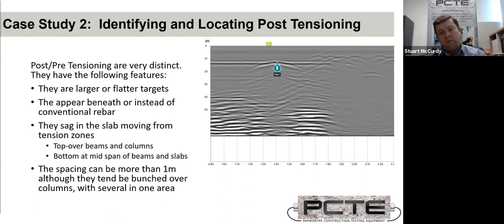So the first time you find them, close to an edge, they're going to be closer to the surface, and then they're going to move down and then come up again. Also, they're irregularly spaced. So with rebar, every 150 mil, you're expecting another one. With post-tensioning, you might have a bundle together, and then nothing for a meter, and then another bundle of post-tensioning strands. So those are some of the key things that we're looking for when we're scanning.